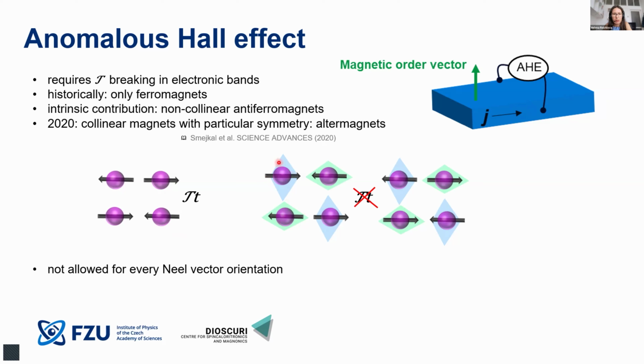However, once we also consider the non-magnetic atoms, then, for example, by changing the orientation of this spin, we cannot get to this picture by any translation or inversion, right? So then we again have the symmetry broken, and the anomalous Hall effect should be allowed. So in this most simple picture, the anomalous Hall effect should clearly distinguish whether we have an antiferromagnet or an altermagnet. From that perspective, and from the fact that it's relatively easy to measure experimentally, and that we do not need any interface, any injection from one material to another, we are not so sensitive to interfacial symmetry breaking effects, which always complicate the interpretation of experimental data.